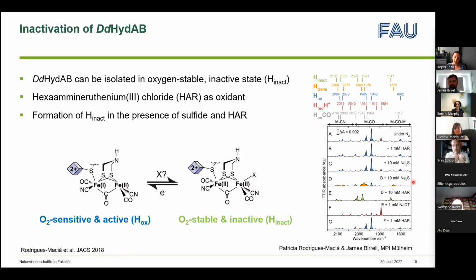But if we combine oxidant and a sulfur source, we see slight changes to these yellow peaks that are named H-trans, and further addition of oxidant then forms the H-inactive state, the oxygen-stable and inactive state that we are interested in. This is not a dead state, so the enzyme in this state can be reactivated under reducing conditions to yield the active oxidized state again. So the first goal that we had in our collaboration is to study how this inactivation works.